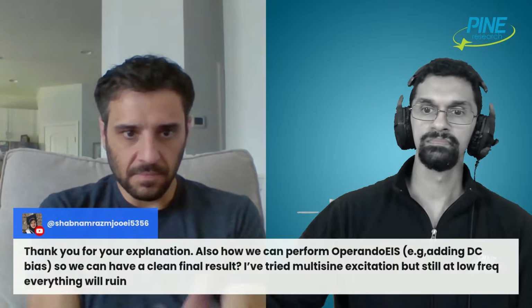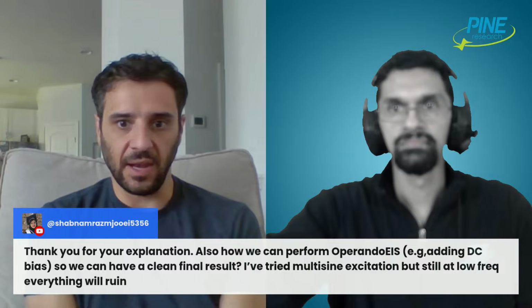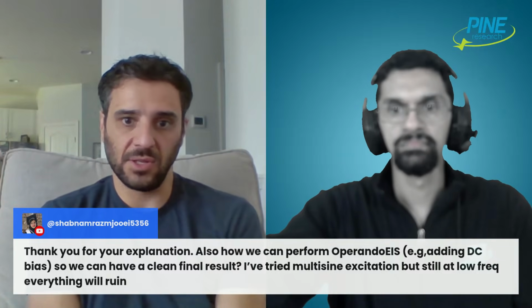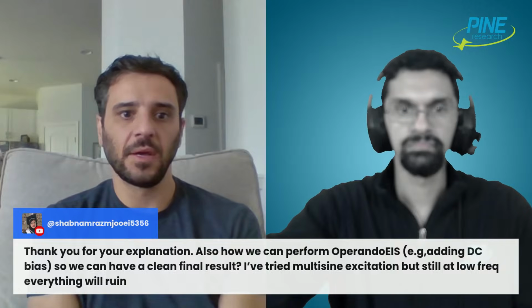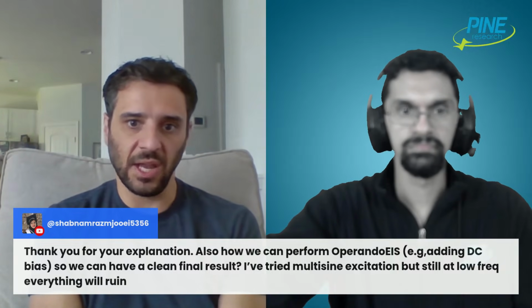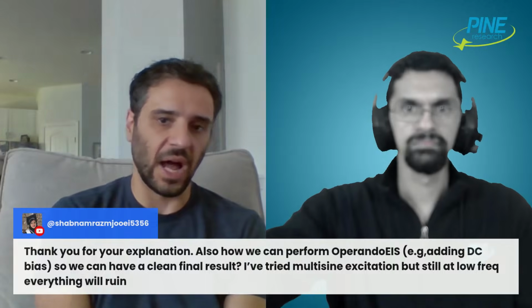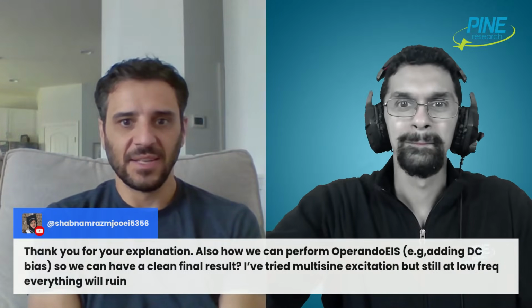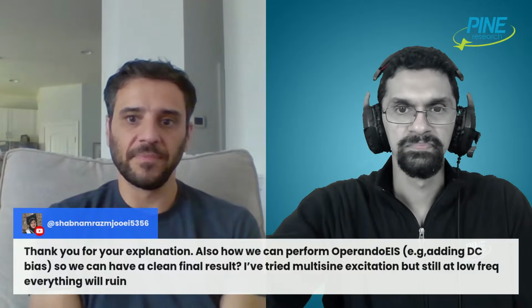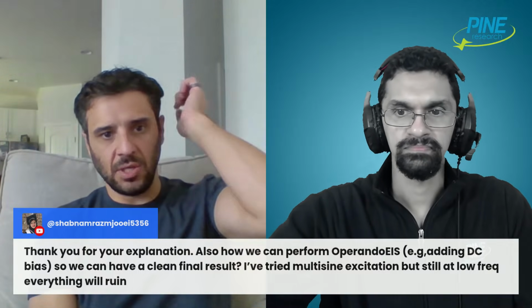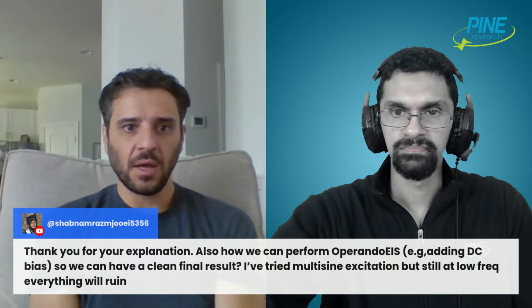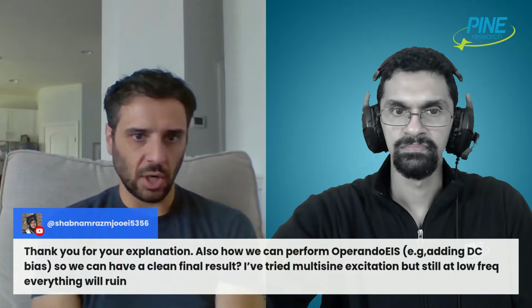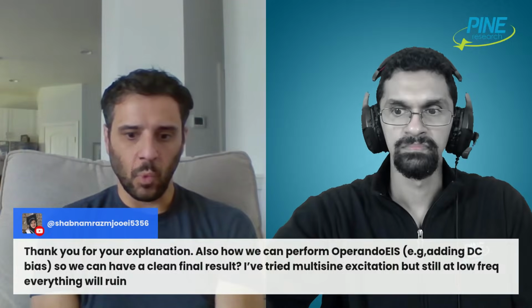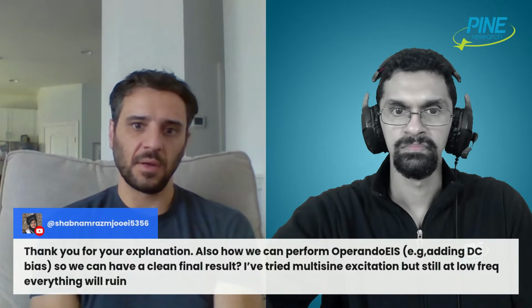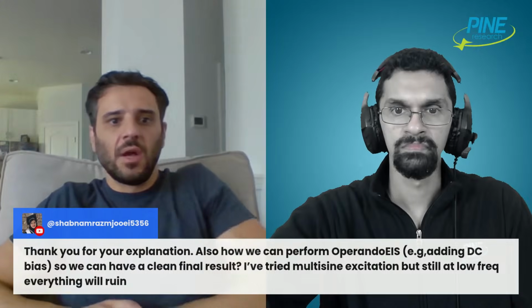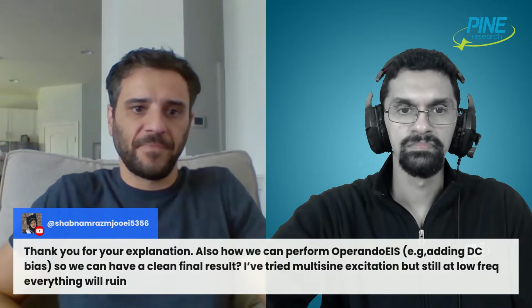I don't know that I can, in good conscience, try to recommend that. It just can't be done. It can't be done accurately. You could do a baseline correction and fudge the data. That would be sort of like lying. But it's not really fundamentally possible. So your better bet is to try pausing the charge-discharge process, waiting for it to stabilize, running impedance, and then continuing your charge-discharge if you have to do low-frequency impedance.